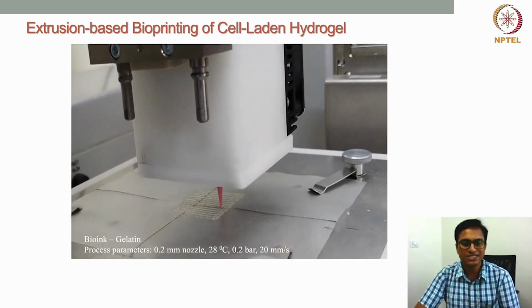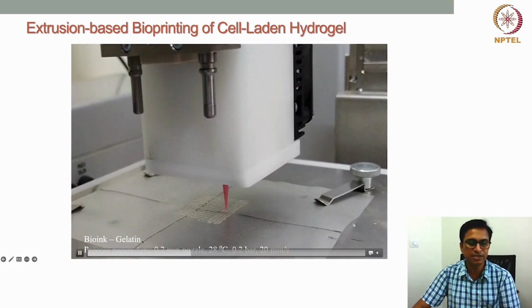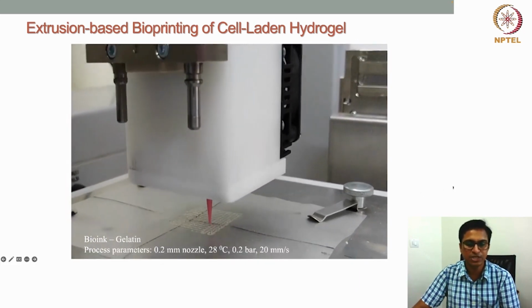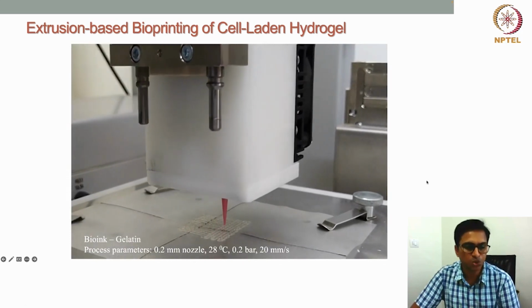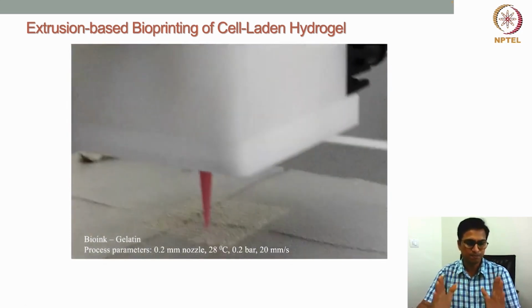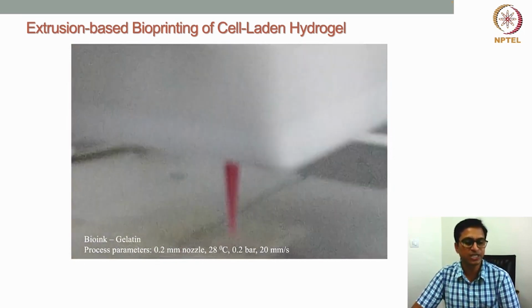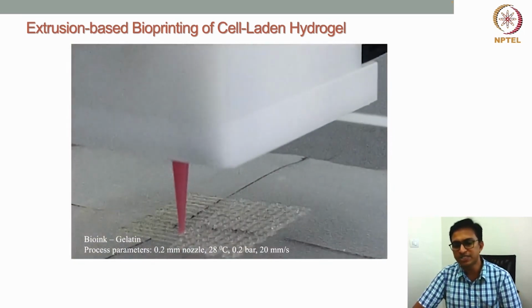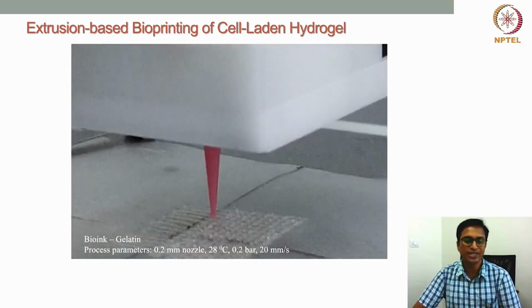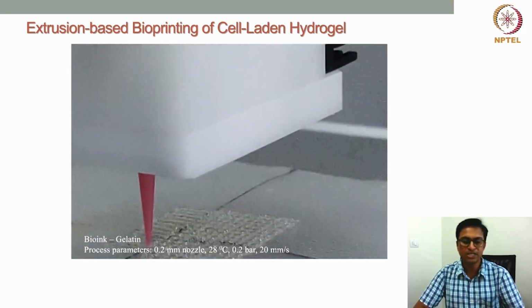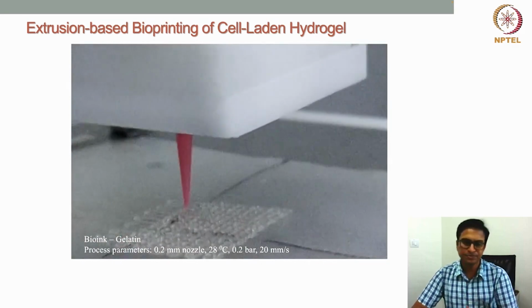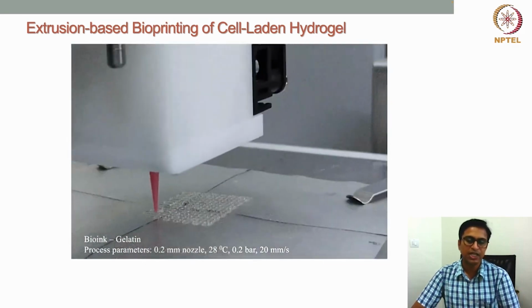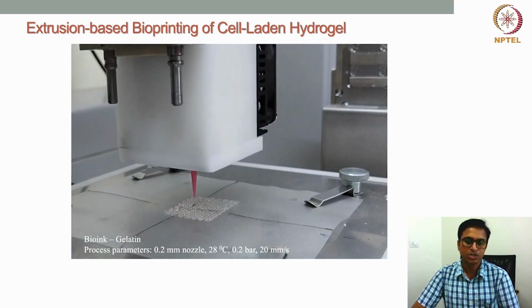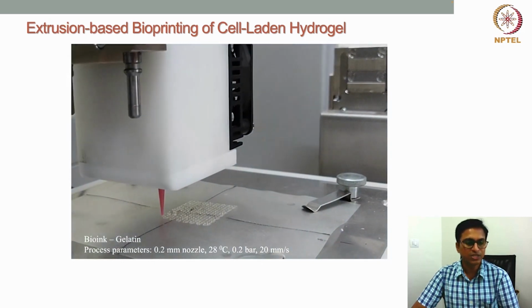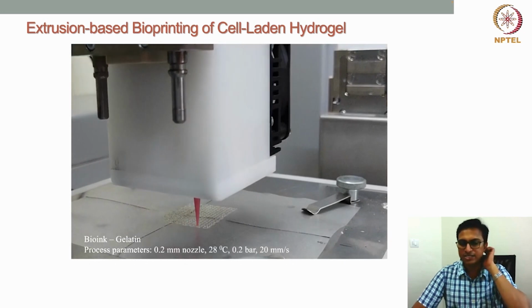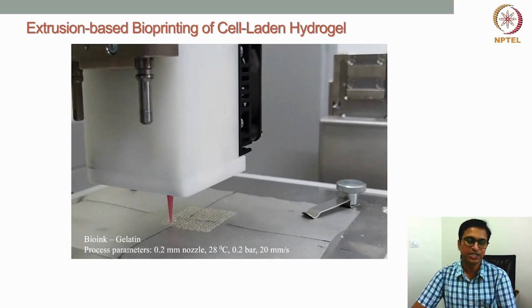Now here, if you can see, they are the process parameters. As I mentioned earlier, the process parameters are very important. Here we have mentioned the process, like we have used a 200 micrometer nozzle, and the printing temperature is around 28 degrees centigrade. We have applied pneumatic based extrusion pressure, where the pneumatic pressure is almost 0.2 bar, and the next thing is the print speed, that is 20 millimeter per second. So that's what we have used here, a lattice structure that is shown here, printing a lattice structure with cell-laden hydrogel.